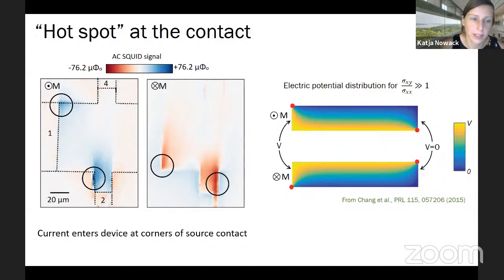All right, and this is at least somewhat expected if you take a more bulk perspective of what is happening in your device. What I mean by this is that in the quantum anomalous Hall state, you have a quantized sigma xy transverse conductivity, and you have a longitudinal conductivity sigma xx that is going towards 0. So you're in a material that has an extreme Hall angle, or extreme ratio of sigma xy by sigma xx, that is much, much larger than 1.